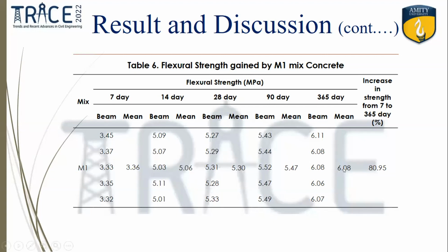As you can see, for mix 1, the 28th day flexural strength was 5.30. The 365th day, that is 1 year strength, was 6.08. The increase was 80%. But in mix 2, the increase was 82%. So in both the tests, compressive as well as flexural, the M2 mix stands superior when the increase in strength is considered. Though the instantaneous strengths were lesser, we can compensate.